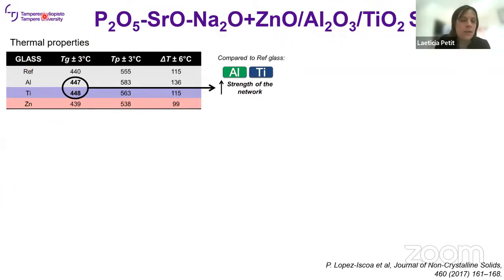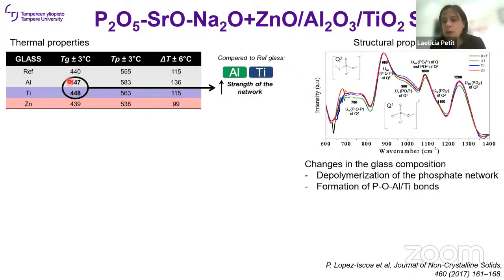So here you have a systematic study to characterize the glasses. So we do the thermal properties of the glass, and when we add aluminum and titanium, we increase the glass transition temperature. So we use again the infrared spectroscopy to compare the structure of the glasses. When we add aluminum, titanium, or zinc, we have a depolymerization of the glass network, as evidenced with the decrease of this band here and of this one as compared to this one. And so we have less Q2 units and more Q1 units. So these units here, they are forming the phosphate network.